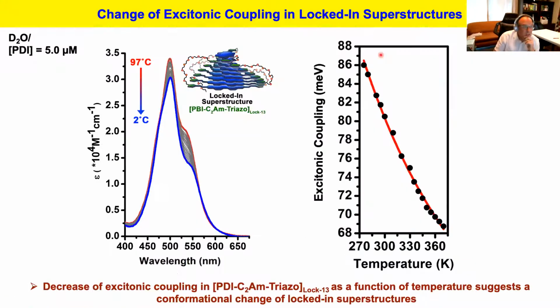And what we can do is calculate the excitonic coupling as a function of temperature. And what we see, of course, is a decrease as a function of temperature. Again, that tells us that as a function of temperature, there is still some structural heterogeneity happening as we are changing temperature. And that makes sense, right? Because essentially you have a solvation sphere around the ethylene oxide side chain that's going to be disrupted as a function of temperature. But the point that I want to make here is that even at high temperature, we are still maintaining a decent excitonic coupling. So even though we do have some structural heterogeneity in these samples, we are still maintaining decent electronic coupling between them. So that was the first indication that this tethering system is allowing us to develop robust nanoscale objects, I would argue.